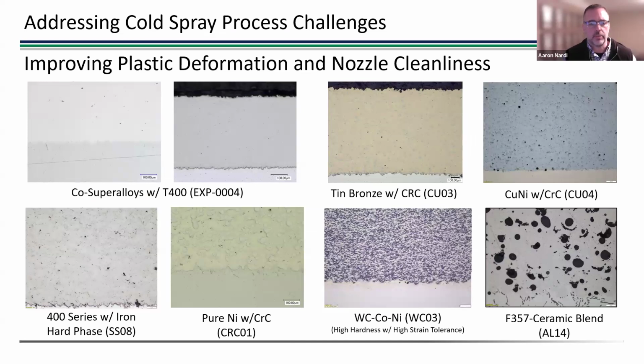These are just a variety of different materials that have been developed over the years. Again, I mentioned before, these blends are very unique to cold spray because nothing that you put through the gun is going to melt. So it all ends up in your deposit in that solid state, in the same state that you put it in the powder feeder. The upper left here are some cobalt superalloys. These are very high temperature wear materials that have been created specifically for the aerospace industry. They have a need for very high temperature wear capability. See some bronzes, copper nickel based materials, iron based materials, 400 series, a variety of austenitics and so forth as well. And then hard facing materials like tungsten carbide, and then some aluminum blends.